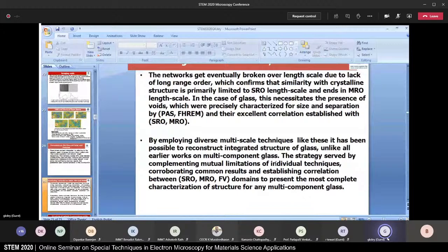So this is the recipe for analyzing such complex structures, and we feel that this recipe can be utilized for studying other structurally disordered solids around us. That is, determine the short range order, determine the medium range order, and determine the location of these voids inside these structures. And then you can resolve many structures, not just glasses, many structures. And in this, the transmission electron microscope has a very important role to play.